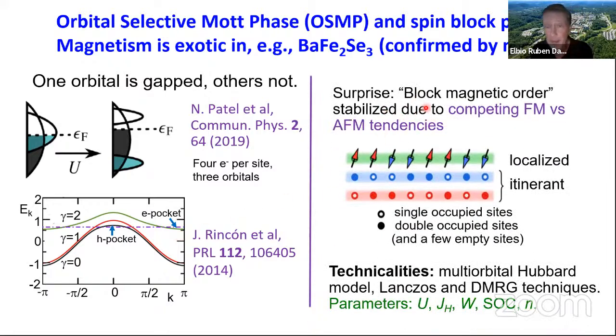So one of the surprises that we found in this early work in 2014 is that the magnetic order comes in the form of blocks. There are regimes of parameter space which are canonically ferromagnetic or staggered up, down, but there are robust places in the phase diagram where you have, for example, two spins up, two down, two up, two down. This is the localized degree of freedom. And for the itinerant, I am not showing the actual arrows, but they all have their spin and they align with the localized due to the Hund coupling. So overall it is an entity that has two up, two down, and so on, right?